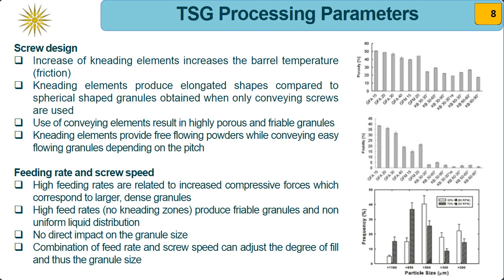This is something you can easily see on the top right graphs, where we have a representation of the porosity when using different elements. So, for example, we have a high porosity of the granule when we use conveying elements with a pitch size of 15 millimeters, followed by 20 millimeters, 30, 40, and so on. And eventually, the less porous granules are formed when we use kneading elements. The same trend we can see in the middle graph, where it accounts for friability. Kneading elements provide free-flowing powders, while conveying elements give easy-flowing granules depending on the pitch size.